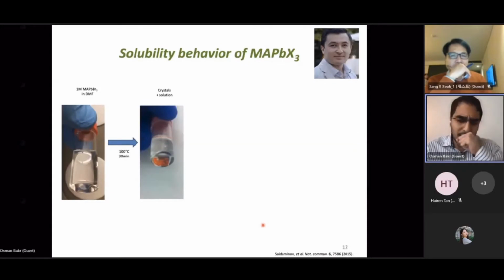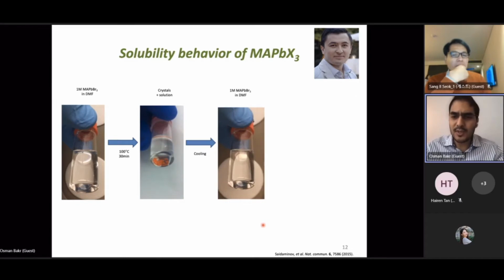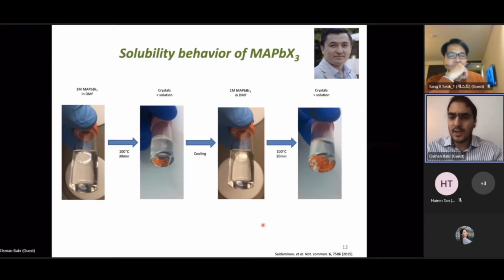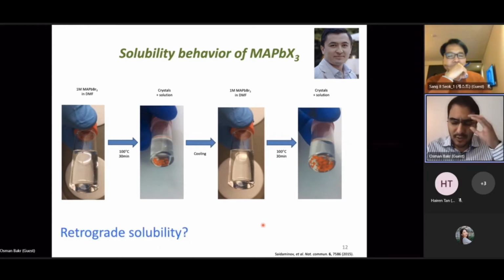So the discovery came when my postdoc Maksud noticed that when we dissolve or saturate a solution of perovskites in a coordinating solvent, and you raise the temperature, you start noticing crystals forming, precipitation happening. So this was very strange because normally when you raise the temperature, more material would dissolve. But in fact, when we raised the temperature, material precipitated. When we cooled the temperature, the material dissolved. And we kept doing this over and over, and we found this is a very reproducible phenomenon, and it's called retrograde solubility. So it's called inverse crystallization.